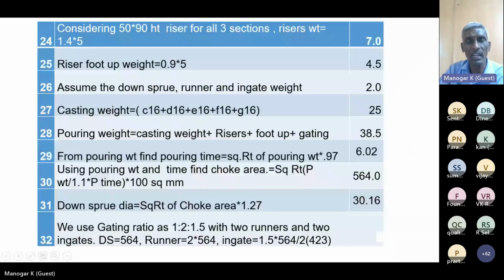Considering the riser diameter and height, riser weight is 7 kg, riser foot weight is 4.5 kg. Assume a down sprue gating system, and the casting weight is 25 kg. So now the pouring weight is 38.5 kg. And from this, find the pouring time. Pouring time is based on the square root of pouring weight. And from this pouring time, you find the choke area, that is the square root of pouring weight divided by 1.1 times the pouring time. That is coming to 30.16 mm diameter.